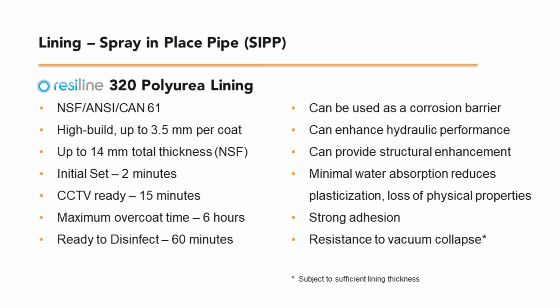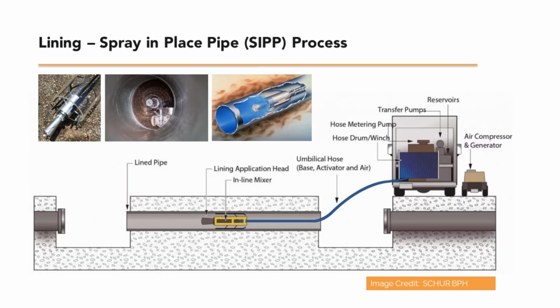With a build rate of 3.5 millimeters per coat and up to a total thickness of 14 millimeters, this polymer can be used as a corrosion barrier to improve water quality or hydraulic performance, or to structurally enhance the pipe. The polymer has a rapid cure time, being dry to the touch within about 2 minutes. The surface is sufficiently hardened within 15 minutes to deploy a robotic camera for quality verification, and additional coats may be applied within an hour.